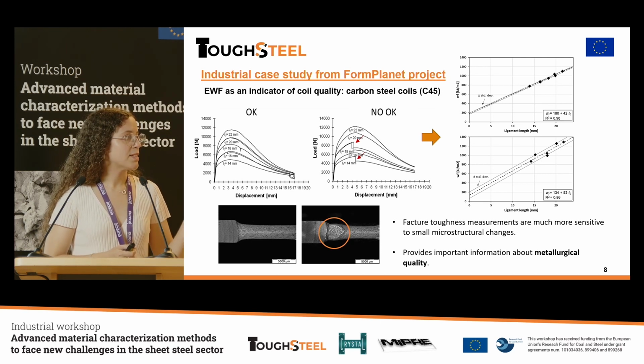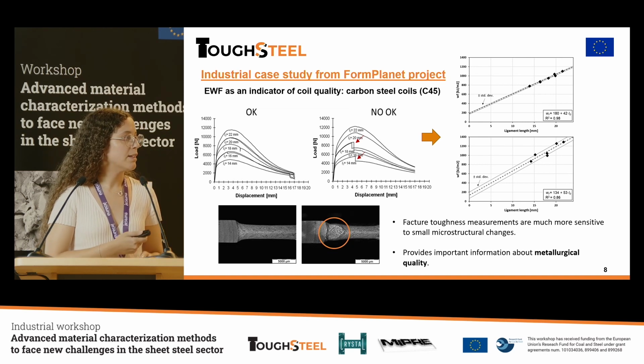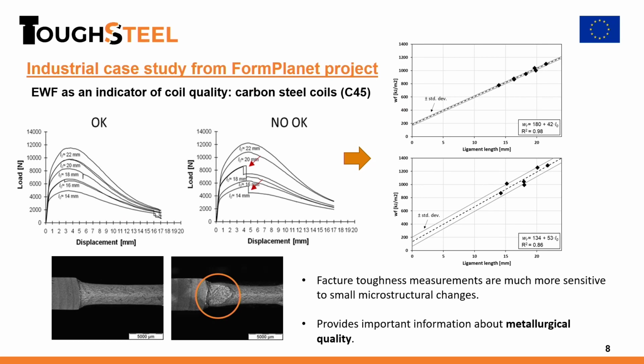In this case, we also examined the fracture surface of these specimens, and we could find that the ones that were presenting these drops in the load had some brittle fracture surface points that indicated that probably in this material there were some instabilities or some defects that were propagating in this brittle mode.